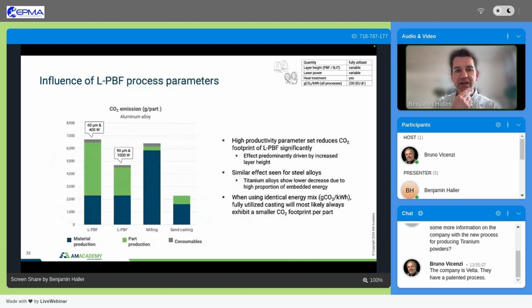Then looking at the productivity, this of course will also reduce the CO2 impact. Here we are comparing a standard process, 400 watt laser, 60 micron layer thickness, with a more productive process. In this example the material remains unchanged, but by increasing the layer thickness and the process itself, we can significantly reduce the carbon footprint. So it's simply a more efficient usage of the printing itself.